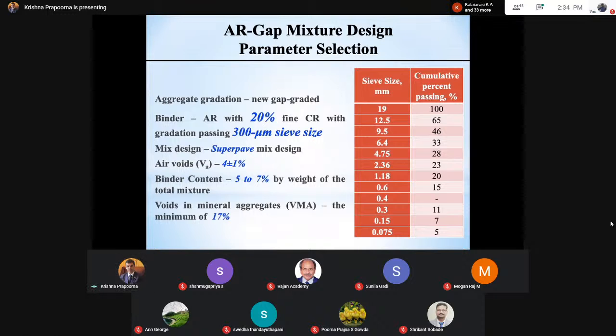This is the formula. This is the final outcome of the report where we actually came up with a new gap graded gradation. You can see here there are a few sizes that are missing. That's the beauty of gap graded. And there are a lot of fines. Anything below 4.75 is all fine aggregate, correct? You people are familiar. You see the number, it's really large. This is all percent passing. If you calculate the retained, that will amount to 50%. That's why it is a gap graded gradation, with a large amount of fines within the matrix.